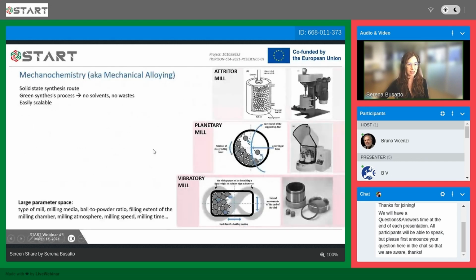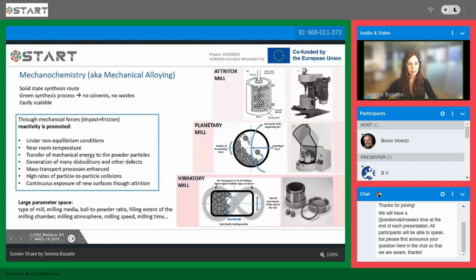Mechanochemistry is, as I said right now, a solid state synthesis route. So this is a green process and it is easily scalable. There is a large parameter space that can be adjusted. And the reactivity of the powder particles is promoted through mechanical forces under non-equilibrium conditions near room temperature by the transfer of mechanical energy to the particles, which generates dislocations and other defects, enhances the mass transport properties and the rates of particle-to-particle collisions, therefore also exposing continuously new surfaces, and all of these promotes reactivity.